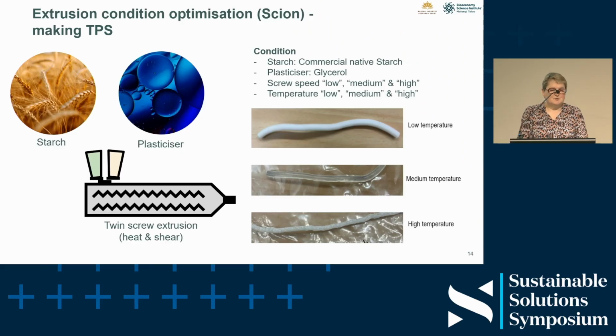First up, because we didn't have a lot of our bread starch extract, they worked with a commercial native starch, added glycerol, put it through a twin screw extruder to work out what was the best process that might work with the bread starch. You can see at the top we've got the low temperature, it's not fully plasticised, and as the temperature went up we ended up with a translucent product with a medium temperature. And then they proved that the temperature and screw speed did not impact starch crystallinity, which is good because we don't want crystals formed, and the higher screw speed was easier to process, so that gave us the conditions to test with the bread starch.